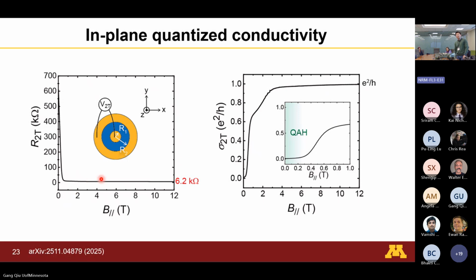We even made ring structures, called Corbino structures. The current flows in the radial direction, so there will be no edge states. The current goes from the inner contact to the outer contact, everything in this direction, and there will be no tangential current. If you convert this to sigma, again you'll see that it saturates at e squared over h. That tells us this quantization happens in the bulk, not on the edge states, because in this Corbino disk structure there were no edge states.